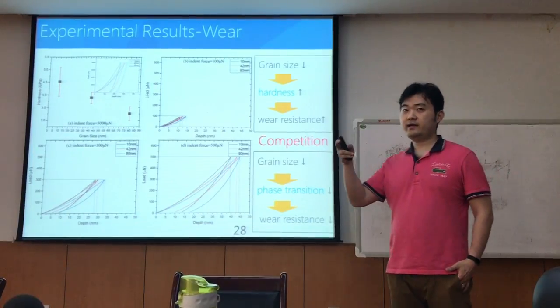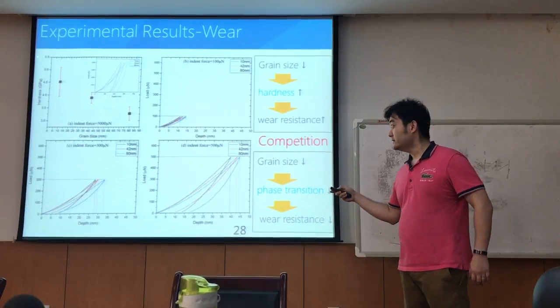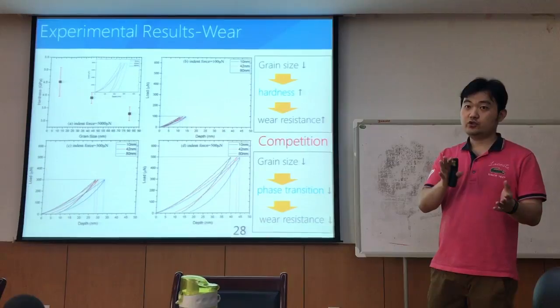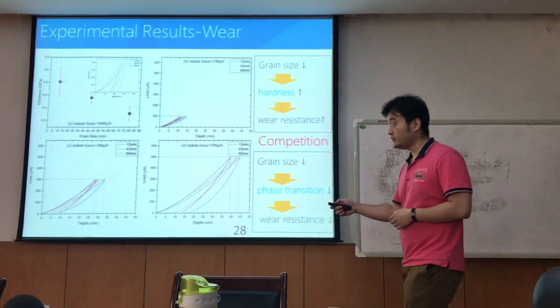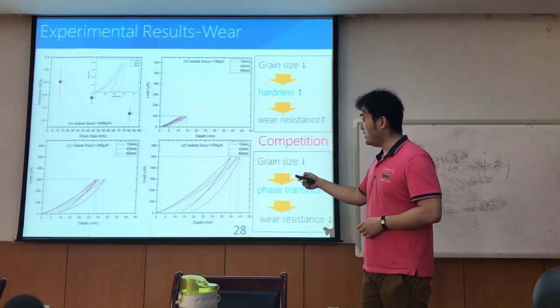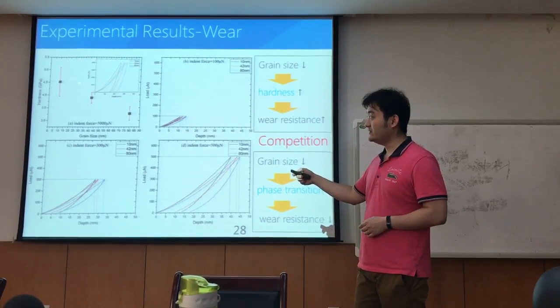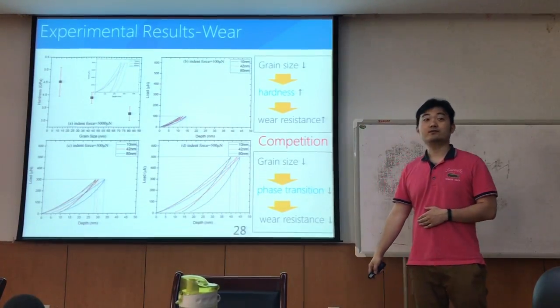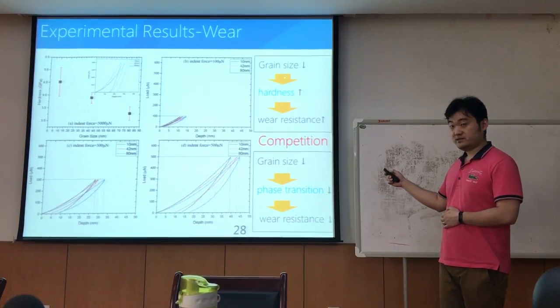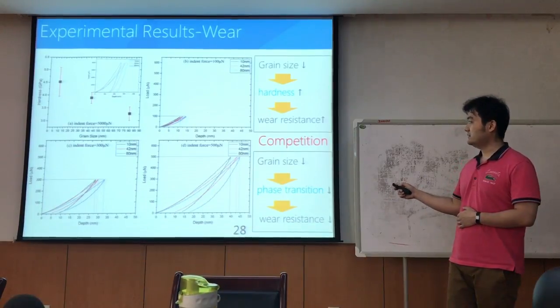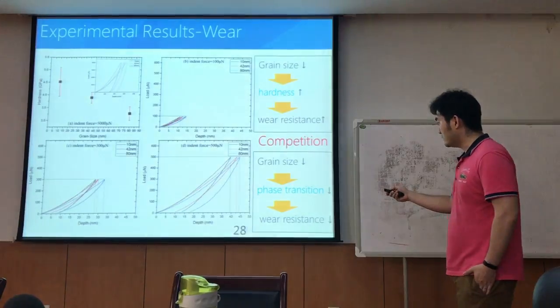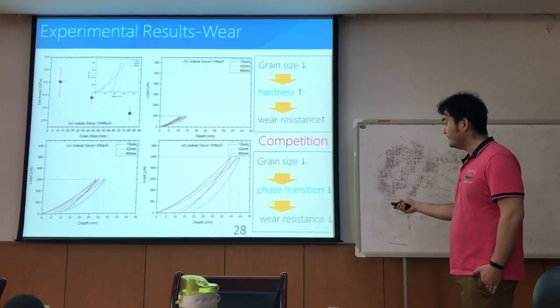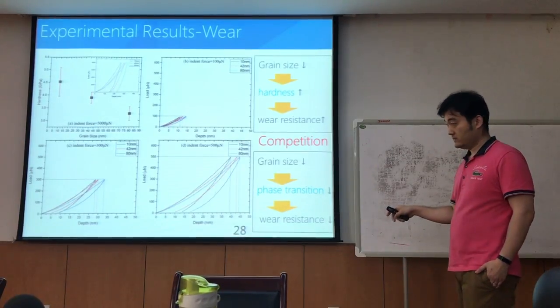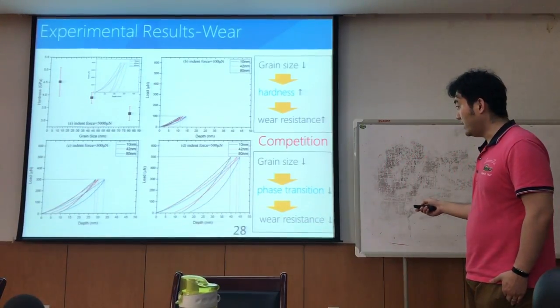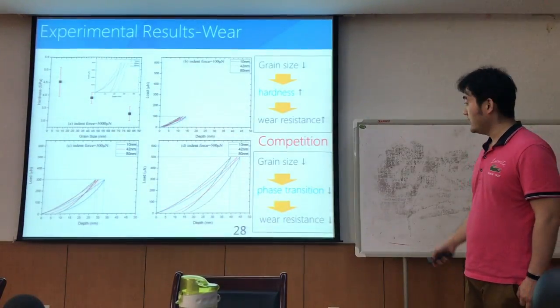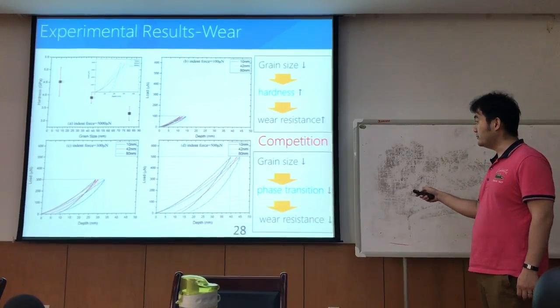And first, we calibrate our sample by testing its hardness, because we know hardness is highly related to the material's wear behavior. And by indentation tests, we find out the hardness of the test specimen is significantly increased with decreasing grain size. Okay, with decreasing grain size. And when the grain size decreases, the hardness increases, and this is good for wear resistance. But as I said before, when grain size decreases, the phase transition will become harder. So, based on others' work, this is not good for wear resistance. So these two opposite effects will compete with each other.